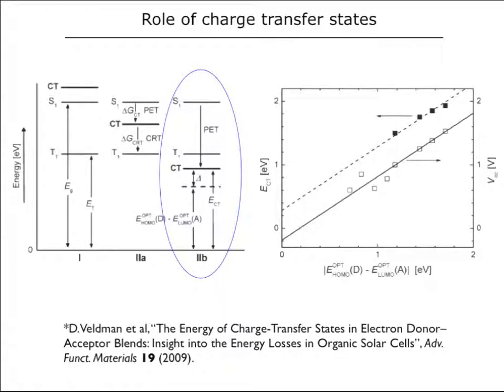But at any rate, recent papers have showed that if you plot the difference between the HOMO of the donor and the LUMO of the acceptor, which should be the maximum voltage of the device, and plot that versus the charge transfer energy measured through spectroscopy, you do get a nice straight line.